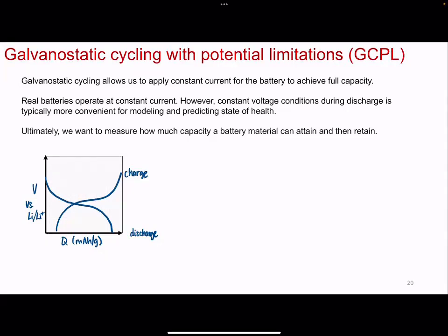So there's got to be some secondary reactions, some side reactions, maybe SEI is forming, and also decomposition of some sort, and there's extra charge that's not related to the original material, right? So if you normalize by grams of your starting material, and you have decomposition and spurious side reactions contributing to charge, you could potentially see something like this.